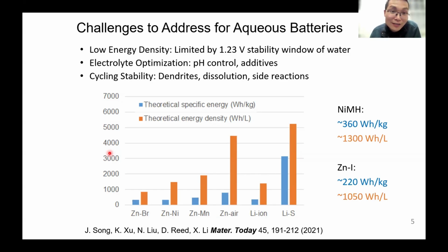But theoretically, if you look at the energy density of aqueous chemistries in this table, this zinc chemistry can theoretically have similar energy density as lithium-ion. Some of the chemistries even have higher numbers. But in practice, lithium-ion can utilize 90% or higher of the theoretical energy, but these zinc chemistries only utilize 10% or so. So that's why in reality they have lower energy. But if you can increase the utilization of these chemistries, then you have energy density that's similar to lithium-ion. And that's what we are trying to do.